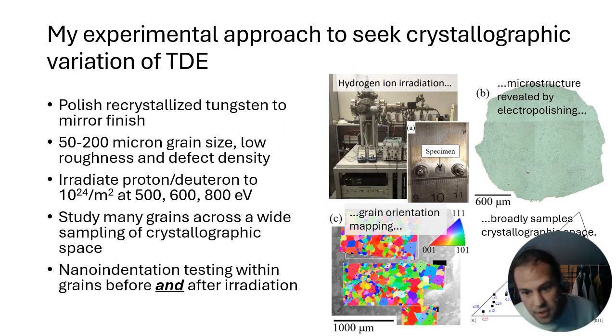Now, what I've done is to look at many grains with much finer spatial resolution than was available in the 1970s. So I have made nicely polished specimens. They have grain size on the order of 100 microns, and they have well-prepared surfaces by electropolishing. I've done ion irradiation with an ion beam to a constant fluence of 10^24 per meter squared at different energies, 500, 600, 800 electron volts. And then I've done EBSD to characterize the orientations of the grains that I've looked at. And so in this one specimen with relatively large recrystallized grains, I'm able to look at a broad sampling of crystallographic space with a large number of different grains.